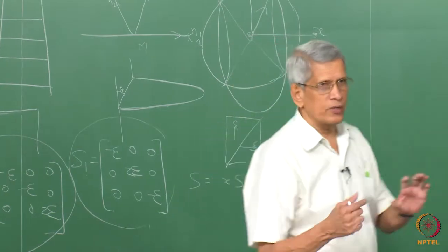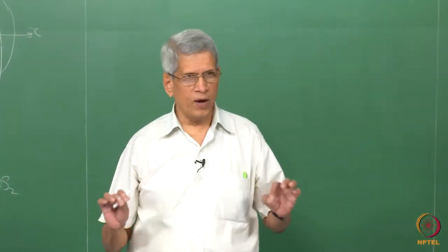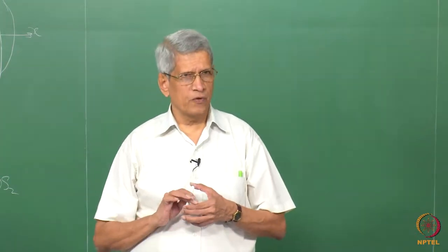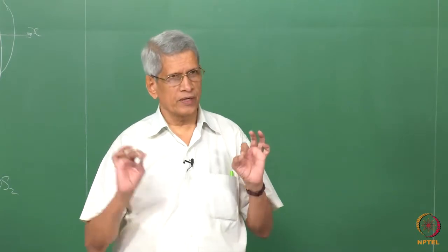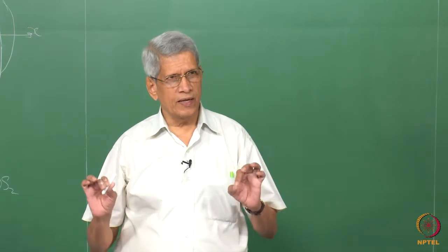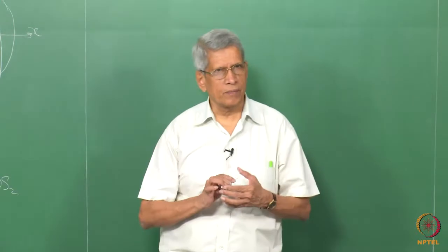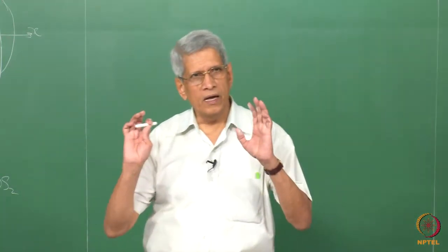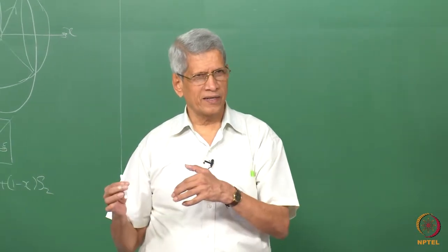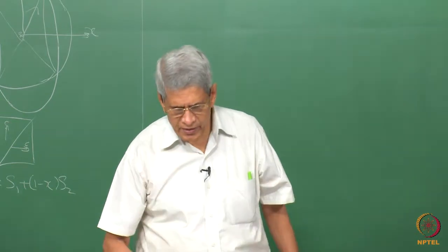Now our aim: we know the values of the strains. If we can find the value of x which will make the total strain for this system minus epsilon in one direction, epsilon in the other direction, and in the third direction 0.